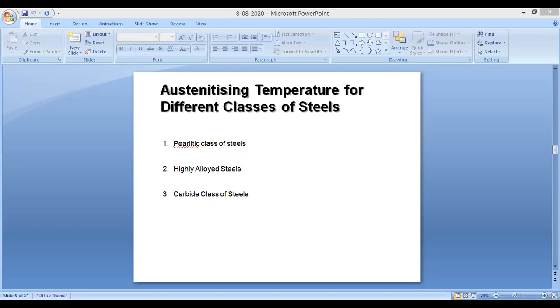The resultant as quenched hardness of steel is less because a lesser amount of hard cementite is present. Secondly, a large amount of retained austenite is obtained as Ms and Mf temperatures are lowered due to increased dissolved carbon in austenite. Austenite is a much softer phase than martensite. Third, the resultant coarse grain martensite is more brittle and one to two units less hard. The quenched hardness is low due to absence of harder cementite, much more retained austenite, and martensite being much coarser.